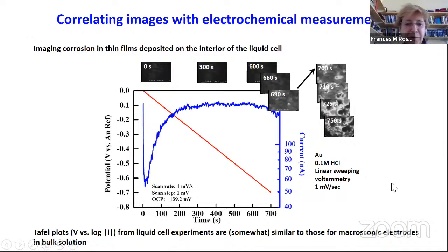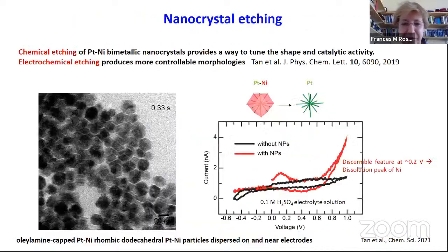We can also do electrochemically driven corrosion, whereby we're slowly scanning the potential and imaging the film as it dissolves. And we can get reasonable electrochemical traces from these experiments to correlate with the results. And other groups have done, for example, corrosion around particles in stainless steels and similar types of experiments.